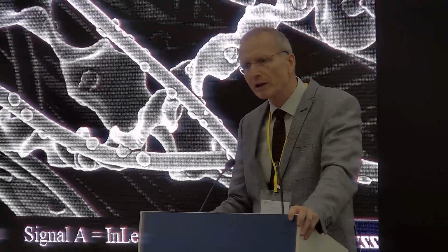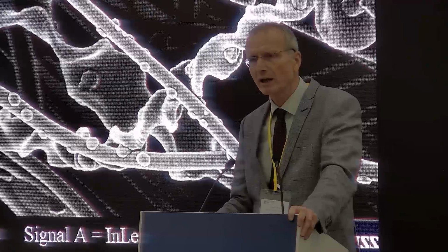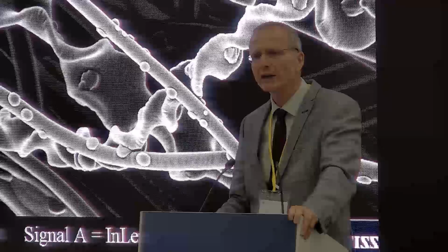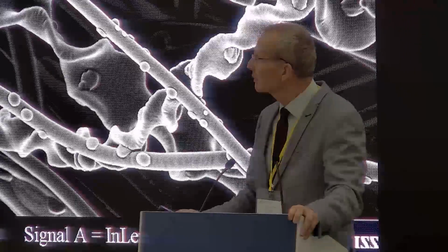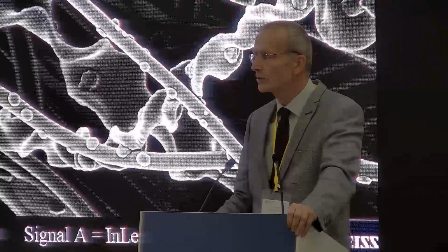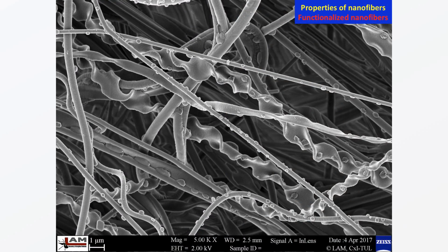What are the polymers we are able to spin? Basically, we are able to spin any soluble polymer. In this case, it is, for instance, polyvinyl butyral, polyamide, which is nylon, polyurethane, polycaprolactone, polyvinyl alcohol, polyethylene oxide, polylactic acid, polyglycolic acid, gelatin, and many others.